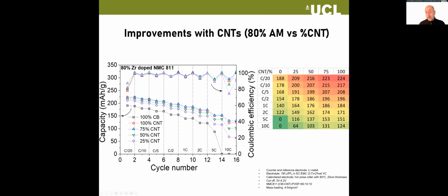So at 10C, for a 6-minute charge and discharge, for essentially an 811 NMC material with a bit of dopant, we're getting really good performance. And if you don't add the carbon nanotubes, it pretty much dies a death. You can see here, at 5C and 10C you don't record anything, so it just drops off the cliff. Now, this is an 80% active material.